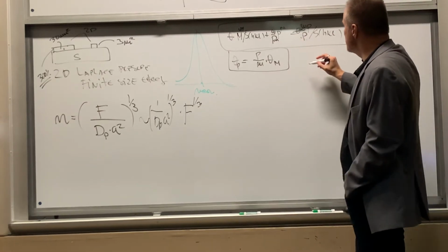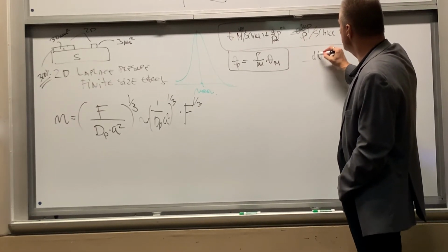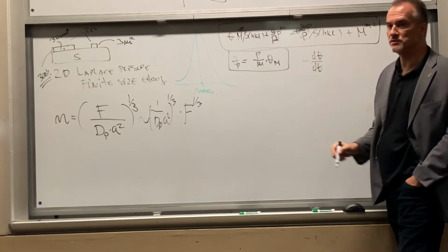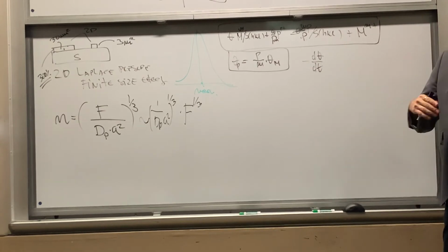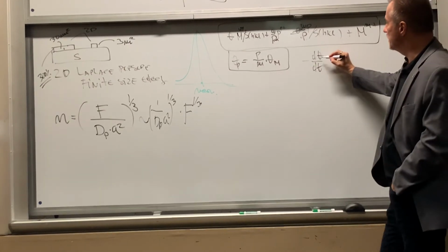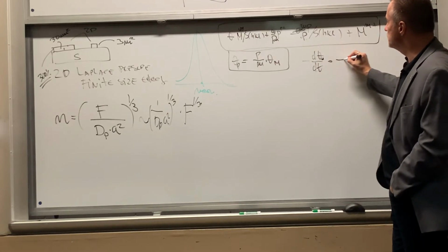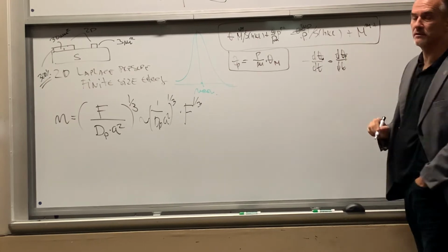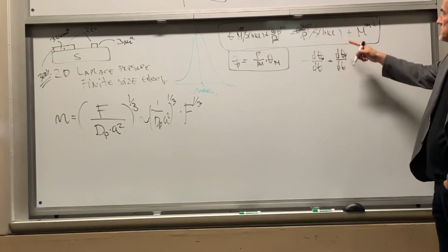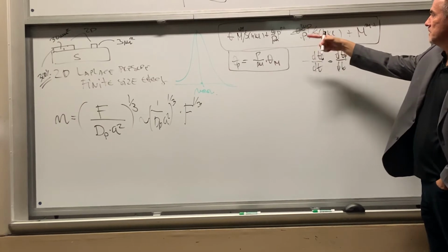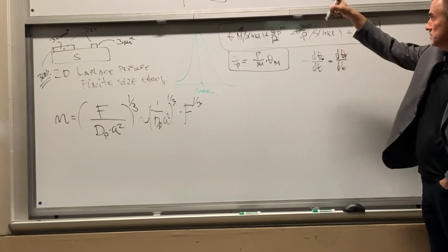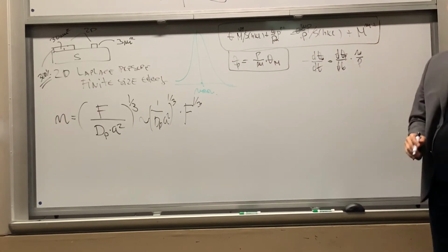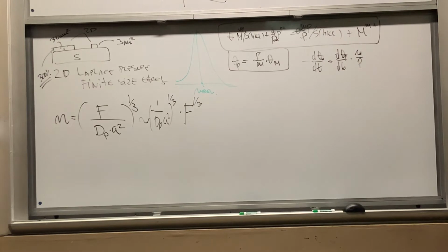What that really means is that minus d theta over dt, meaning reducing the coverage of the UPD layer, and I'm going to call this M, is equal to d theta over dt of P. But it has to have this constant that factors the stoichiometry, so it has to be times M over P, just to make sure that we know what we're talking about, right?